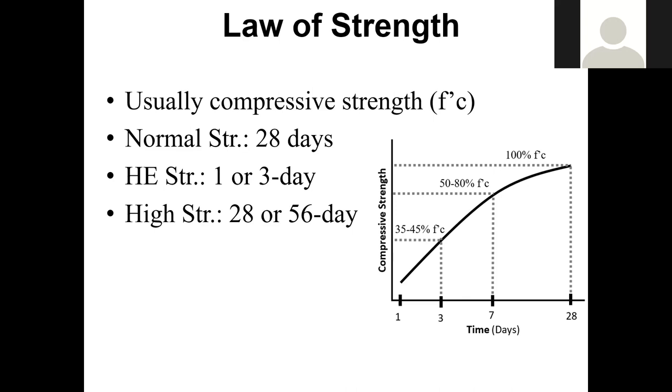after 28 days. But you may see 100, at 56, you may see 120%, or 90 days, you may see 120%, but they flatten off pretty well. You may see at 10 years, you may see double your 28 day number. So I feel like that's a pretty good number to base things off of for your strength.